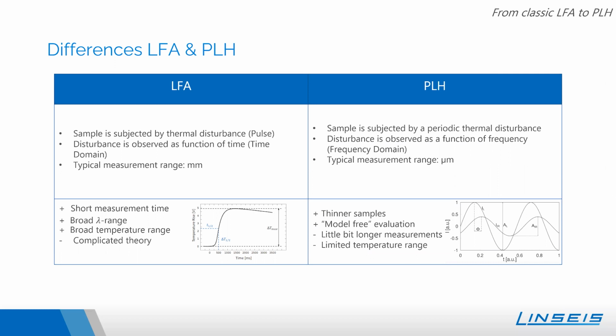The main benefits of the PLH measurement are the possibility to measure very thin freestanding films. And in addition, it's a pretty model-free evaluation. You just have to find the most linear range of data points, and then you can calculate your thermal diffusivity. But on the other hand, you have to count on a little bit longer measurement times. And at the moment, our measurable temperature range is limited.